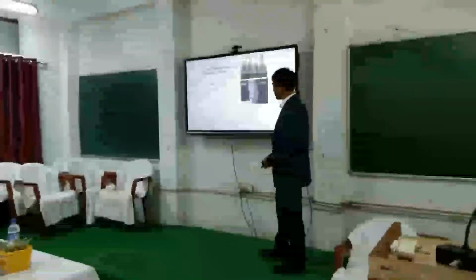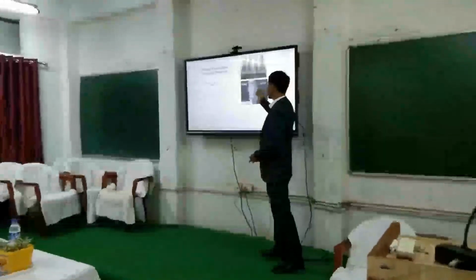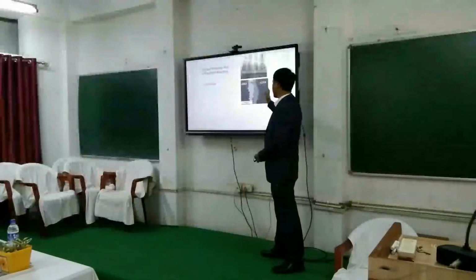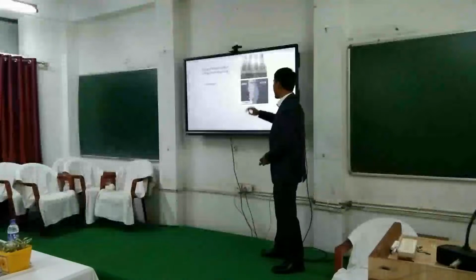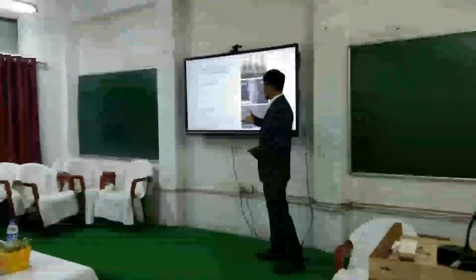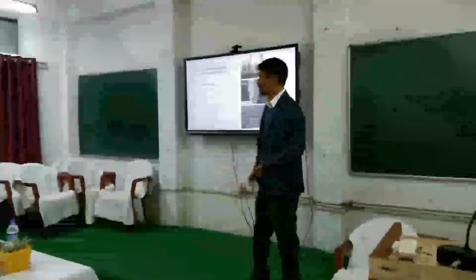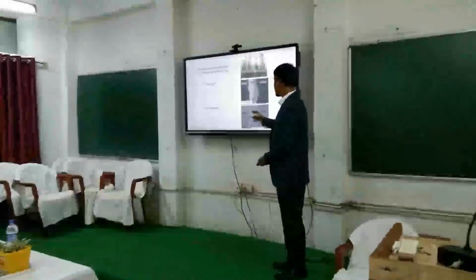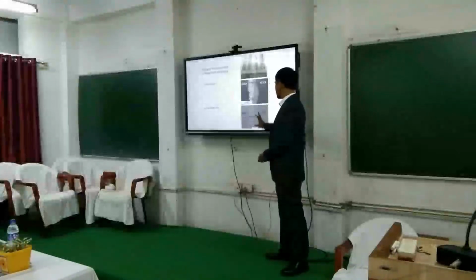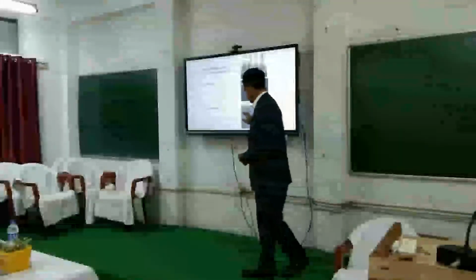And the interlayer that we have chosen is the zinc interlayer. So zinc, you can see here, has fully melted and formed an interlayer in between the aluminum and the magnesium alloys. We have also used other interlayers like active braze alloy. These are also very commercial braze alloys in the form of powder, naturally, and which are also forming reaction zones, and we are getting very good joints with minimal defects.